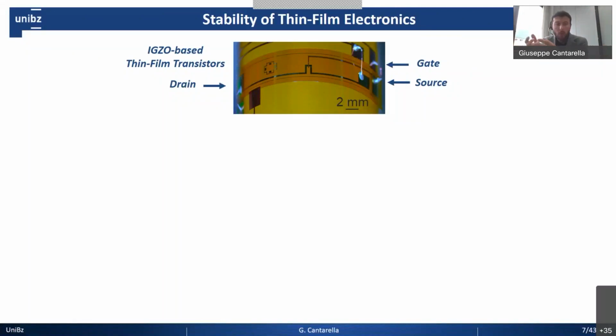If we look at the transistor, the basic electronic component that we deal with, the parameters that we usually look at are, for example, the mobility that we can extract. We know that our semiconductors usually can have a mobility between 15 and 20 centimeters squared per volt second. We also measure and evaluate the threshold voltage, the voltage at which the transistor turns on, and we have the experience that for our thin film technology this number is usually between 0.2 volt and 0.7 volt, roughly.